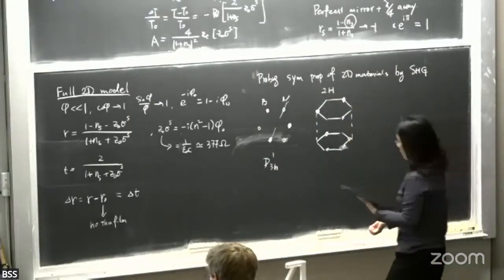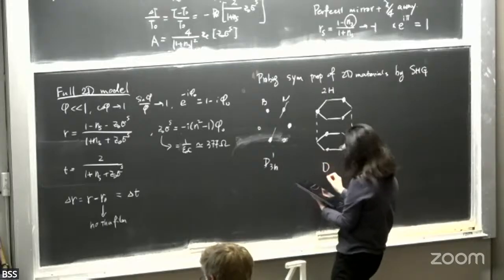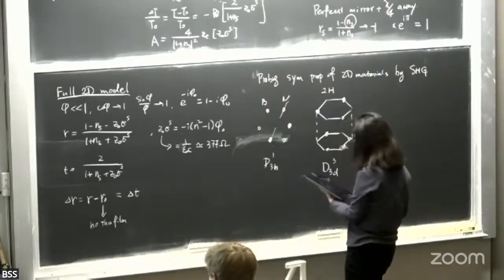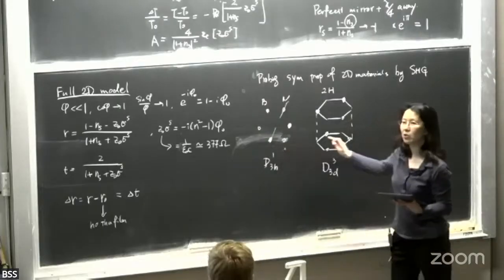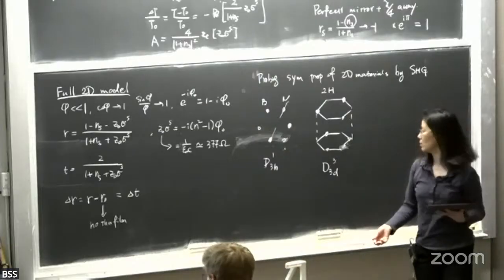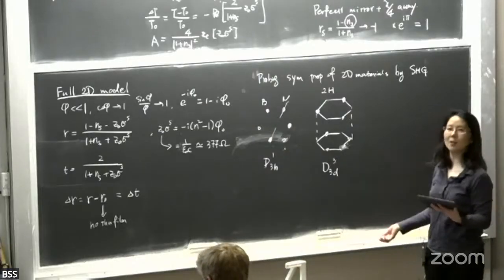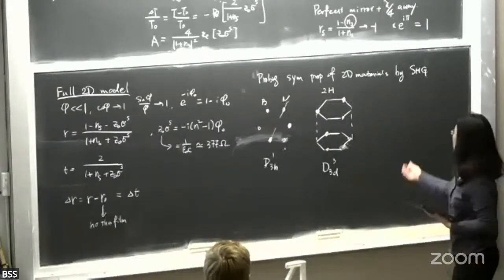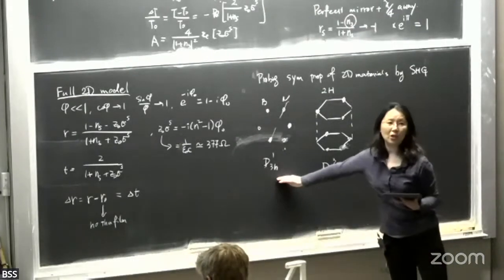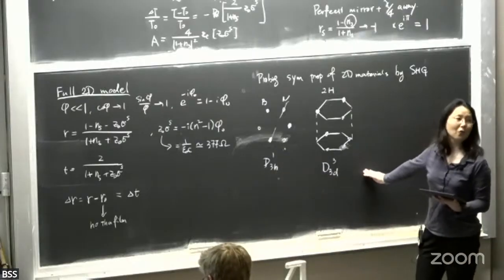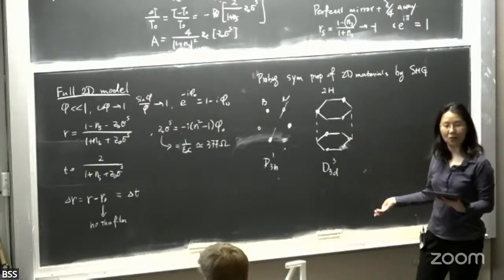In this case, it's a different symmetry group, D3d. So this is not centrosymmetric, this is centrosymmetric, and then three layers will be non-centrosymmetric, and it goes on and on. If you do second harmonic, you get a huge signal from one layer, no signal from two layers, a large signal from three layers, and so on and so forth.